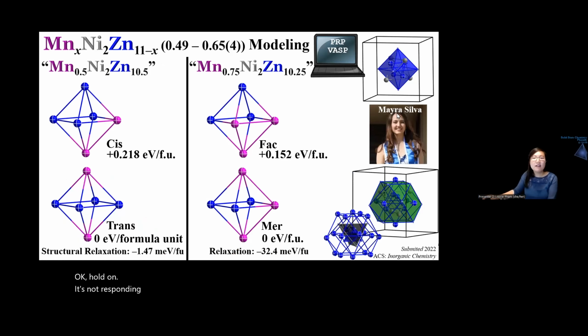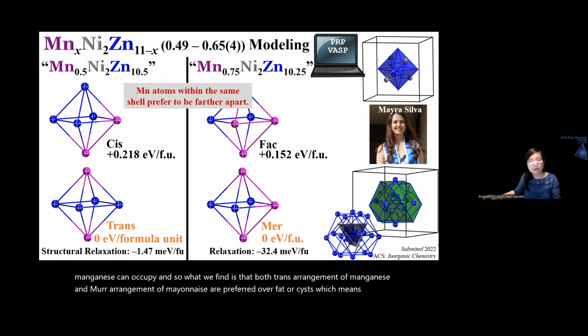Okay, so Mayra did these calculations using resources from UCSD, and what we find is that with a little bit of manganese and then a little bit more manganese, these are the only options that manganese can occupy. And so what we find is that both trans arrangement of manganese and mer arrangement of manganese are preferred over fac or cis, which means that in this atomic arrangement, manganese atoms prefer to be farthest apart from each other.